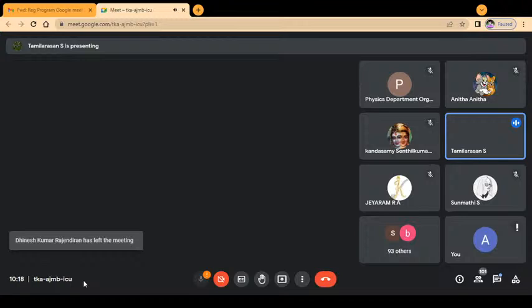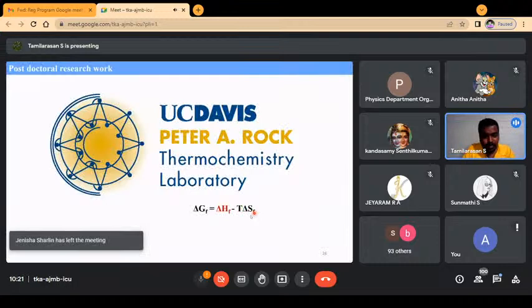We do experimental thermodynamic work, using several different calorimeters. Especially, I will show you this particular calorimeter, Alexis, which is a high temperature oxide melt calorimeter that measures enthalpy of formation. That is an important term in the Gibbs free energy of formation equation, right? Along with T delta S, which depends mostly on the change in entropy. So in this equation, enthalpy of formation is the deciding term unless a material is stabilized by entropy, like high entropy alloys or multi-component oxides. These are entropy stabilized. Unless the compound is of such kind, most compounds' stability is decided by the delta HF, the enthalpy of formation term.